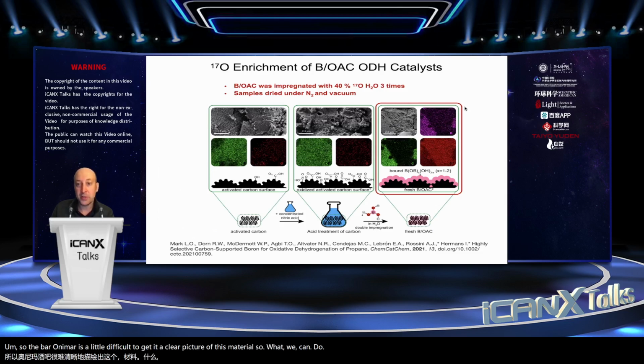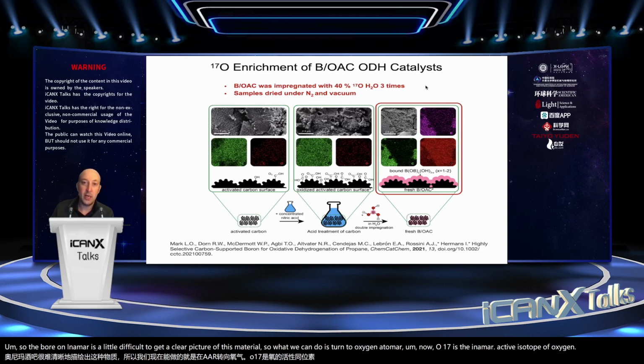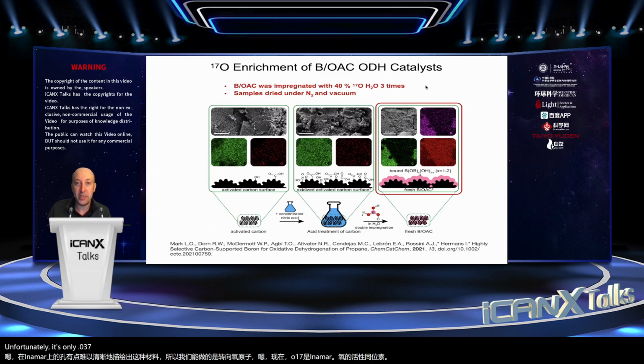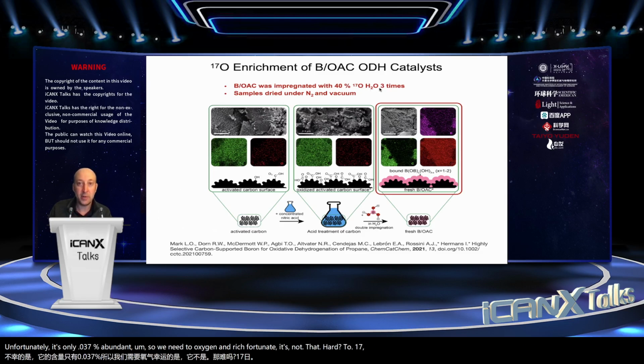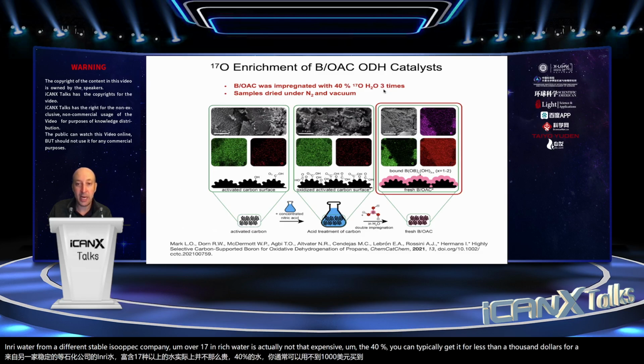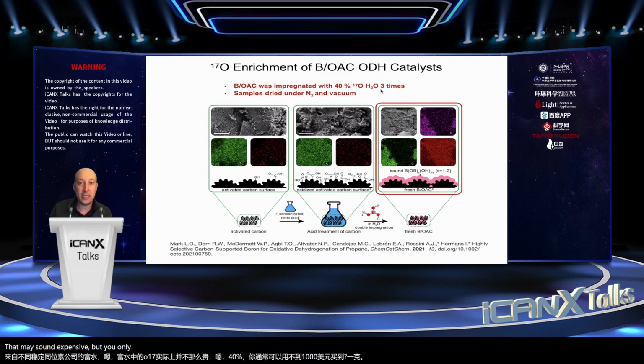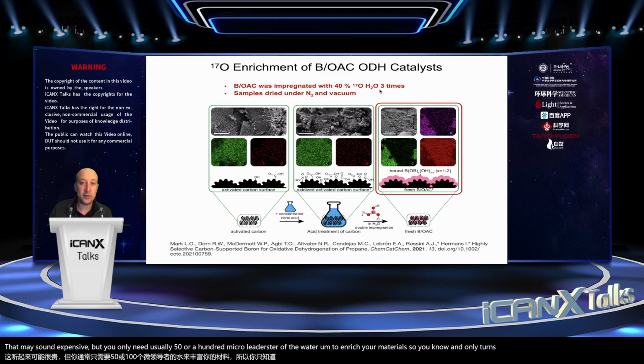So what we can do is turn to oxygen NMR. Now O17 is the NMR active isotope of oxygen. Unfortunately, it's only 0.037% abundant. So we need to oxygen enrich. Fortunately, it's not that hard to O17 enrich these materials. You can just buy some O17 enriched water from different stable isotope companies. O17 enriched water is actually not that expensive. The 40%, you can typically get it for less than $1,000 for a gram. That may sound expensive, but you usually only need 50 or 100 microliters of the water to enrich your materials. So it only turns out to be a cost of say $50 or $100 per sample, which isn't that bad.